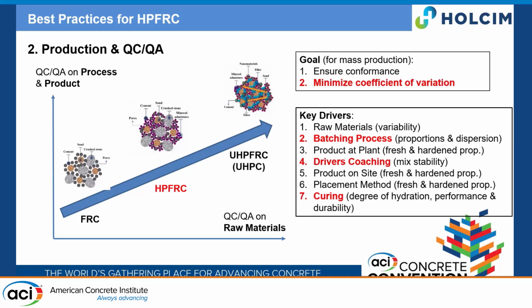In terms of QC/QA, it's the same deal. As we get higher performance, we need to get tighter and tighter in terms of how we control our material, how we control our batching process. This is to ensure conformance, but also to minimize the variability of the performance. One key aspect, especially as we get lower and lower water cement ratio, is that the batching and the sequencing, to ensure we have a proper dispersion and the proper hydration of your matrix, is critical. And how we coach our drivers and how we cure the specimen is more and more critical.